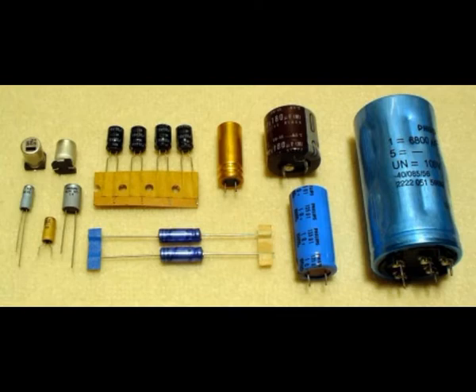The thermal resistance beta depends on the case size of the relevant capacitor and, if applicable, on additional cooling conditions. If the internally generated power losses P_VL, dissipated by thermal radiation, convection, and thermal conduction to the ambient environment, correspond to the thermal losses P_VTH, then a temperature balance between capacitor temperature and ambient temperature is given. Typically, the specified rated value for maximum ripple current in manufacturers' data sheets is calculated for a heating of the capacitor core cell of 10 degrees Celsius for 85 degrees Celsius series, 5 degrees Celsius for 105 degrees Celsius series and 3 degrees Celsius for 125 degrees Celsius series.